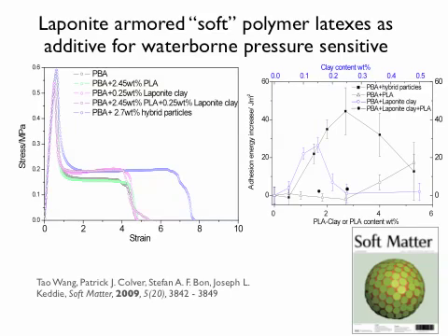So what can you do with this stuff, right? So you've made these particles, and what can you do with it? So this is quite interesting. The advantage of a miniemulsion polymerization is that you can polymerize monomers that have a very low water solubility. So for example, lauryl acrylate has a very low water solubility. And in emulsion polymerization, that's difficult because you have to rely on monomer transport.